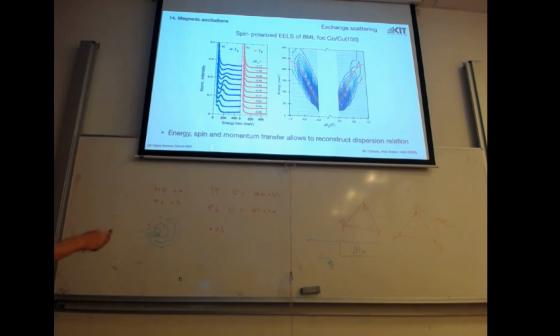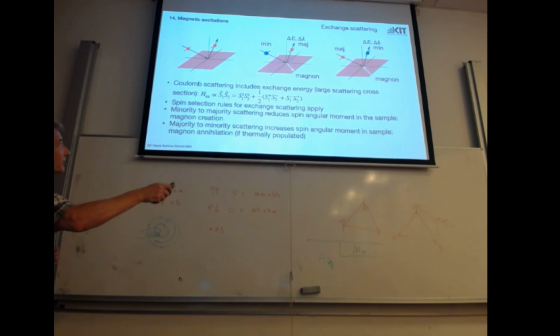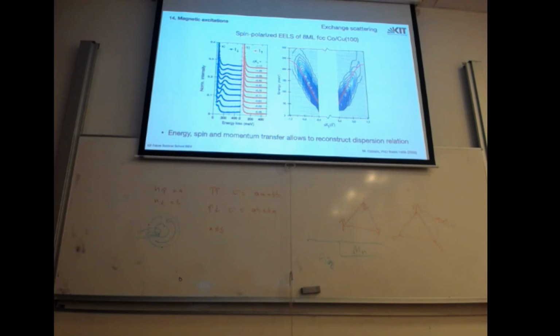So this is data on minority electrons hitting the surface, and we just check what's the energy of the reflected electron. Zero energy loss is the specularly reflected electron without interaction. Most of the electrons are like that, but some electrons are actually reduced in energy, as the energy loss here. And I can vary the direction of my detector. So I collect these electrons angle resolved, so I can change the momentum transfer just like in neutron scattering. And you see the magnon dispersions.